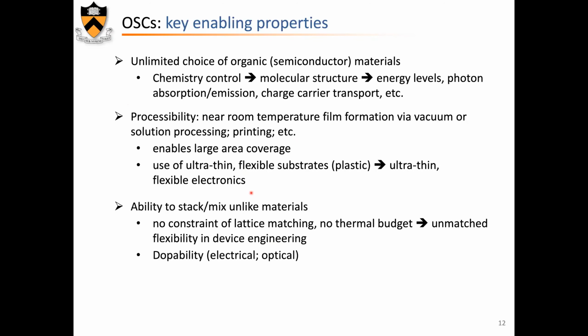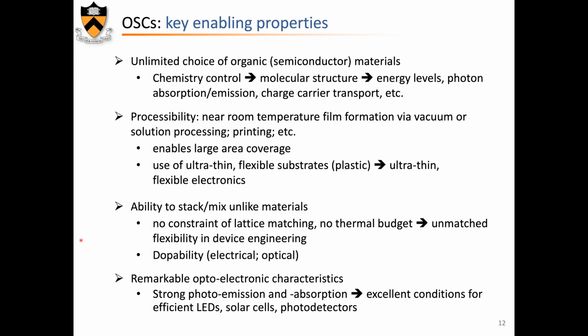The other one, and that is perhaps for me one of the most important, is the ability to stack and mix materials. And I will explain that a bit better. The fact that we do not have covalent or partially covalent bond between atoms in the lattice like in silicon, but we have here van der Waals bond between molecules. There is really very little constraint on lattice matching when you put material B on material A. There's no thermal budget. So there is unmatched flexibility in device engineering, as I will show you in a second. And then finally, of course, the remarkable opto-electronic characteristics, very strong photoemission, very strong absorption, and therefore very good conditions for LEDs, for solar cells, for photodetectors, and so on.